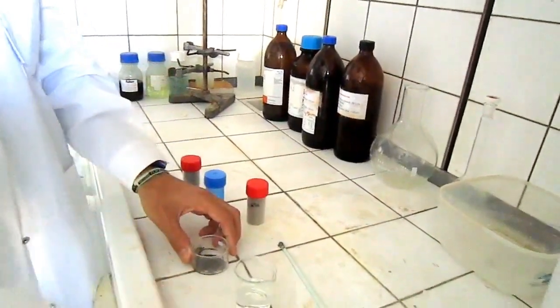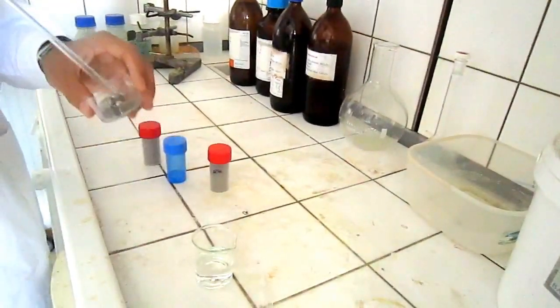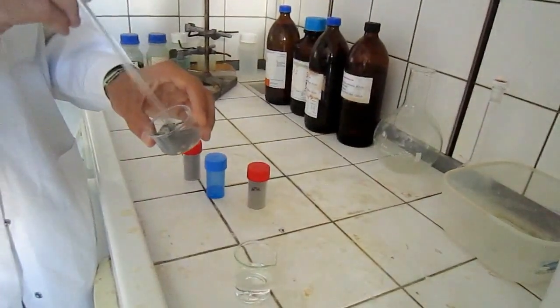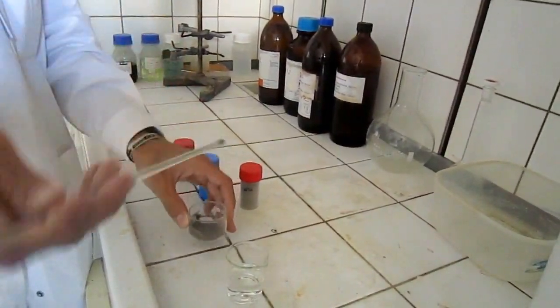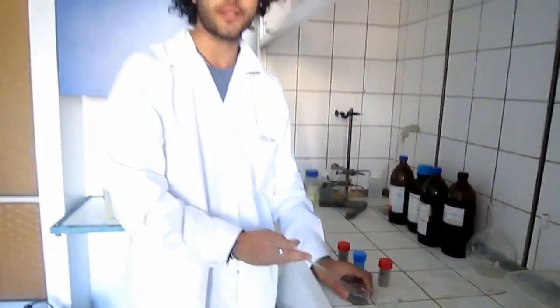We make a slurry, we mechanically mix it, and we cast it in a rubber mold. We make a curing at relatively high temperature, for example 80 degrees, for at least 24 hours.